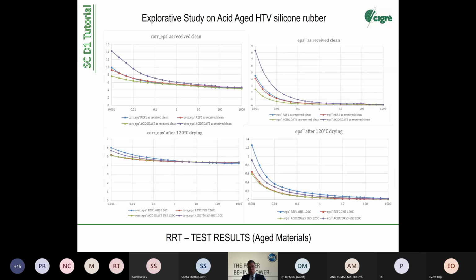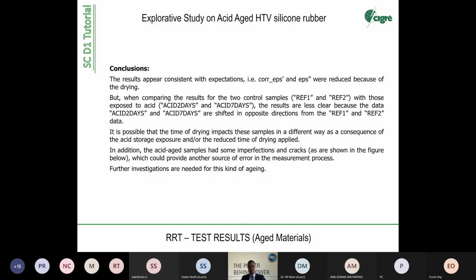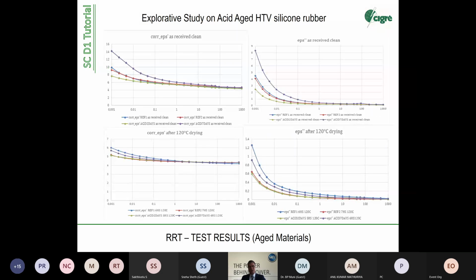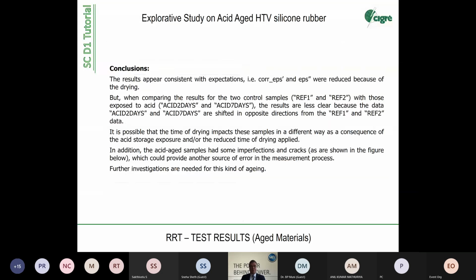Acid aging here. Yes, you see responses, but you see no clear effect of the acid because the acid stays at the surface. And the methods that we have defined are methods for the bulk material, for the volume. So the answer is very easy: we cannot detect surface-related aging effects with such a method. We need to look into bulk materials.